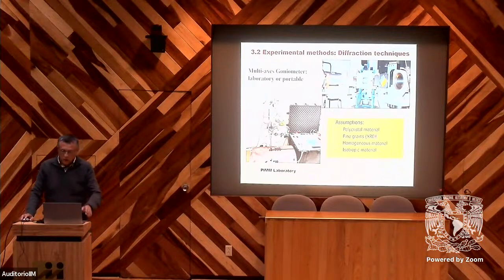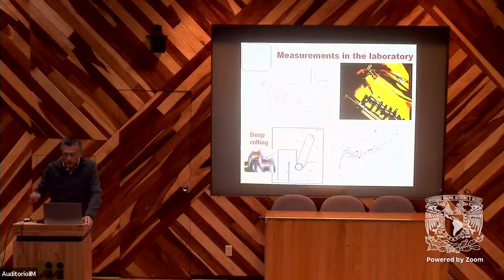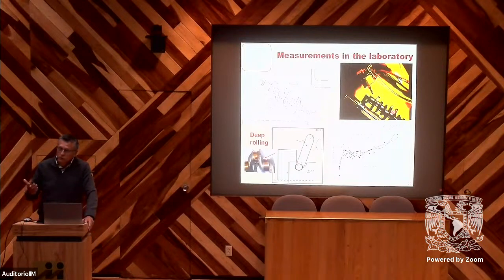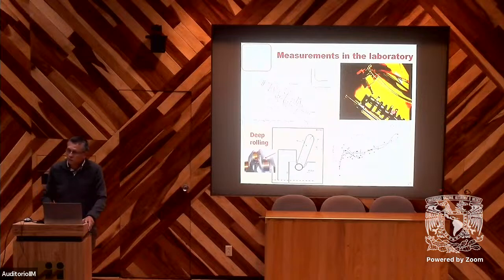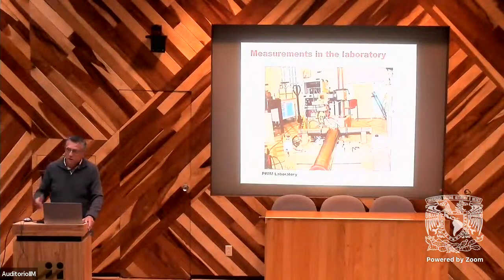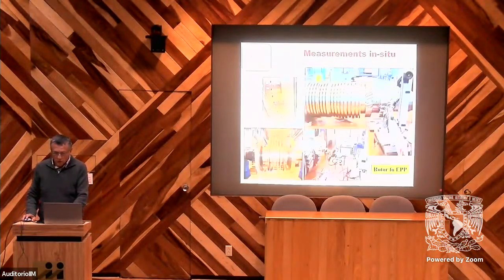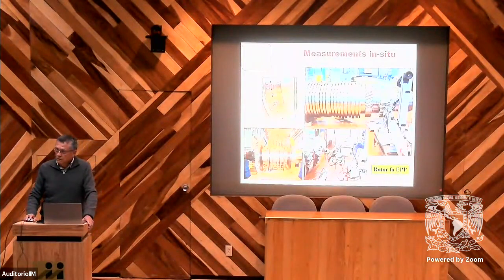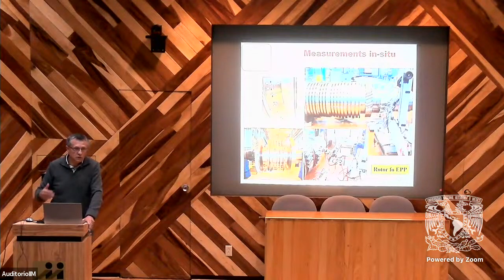So for X-ray diffraction, we consider that we have a polycrystalline material with fine grains because it's a statistical method, and we consider that we have homogeneous materials with isotropic behavior. So we use it many times, of course, for many applications. For example, for automotive, we can study the effect of machining, or here deep rolling on the crankshaft. So we need to understand this to study the fatigue behavior of this component. We have also some applications for the aeronautic field or for nuclear power plants. This is some example of measurement in situ.